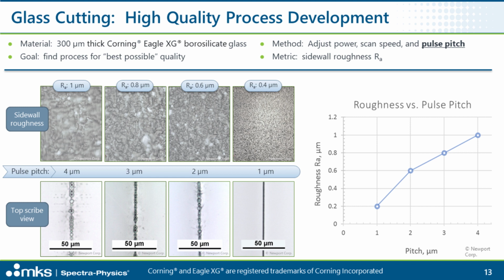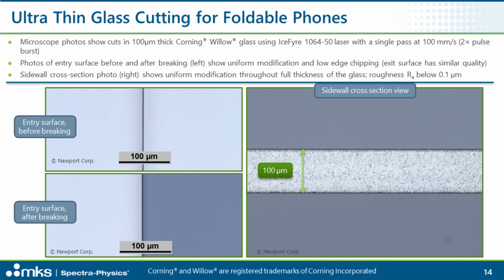So this was a very nice result to see, and we demonstrated this quality and actually improved on the 0.2 micron roughness in the next material, which is a 100 micron thick ultra thin glass. The photo at top left shows the surface view before breaking the glass, a very clean continuous scribe as we saw before in the previous slide. And then once you break, the quality is maintained, and once again, very clean quality, no chipping along the edges to speak of, at least at this magnification.